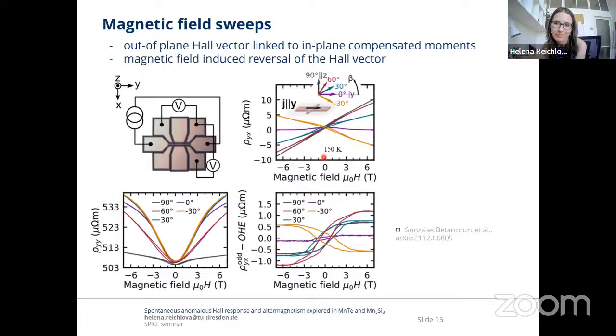One other thing: I'm a bulk person, I don't know much about thin films. Is there any reason to think that maybe there is some effect from the substrate that you're using to grow these films? Yes, the substrate is insulating, right? So you would not pick up the voltage from the substrate, or do you mean something else? It's paramagnetic. Some strain or something like that? Yeah, the strain indeed, right? This is what we think, that the strain induced from the substrate is causing the changes in our Mn5Si3, but not the measured voltage, right?